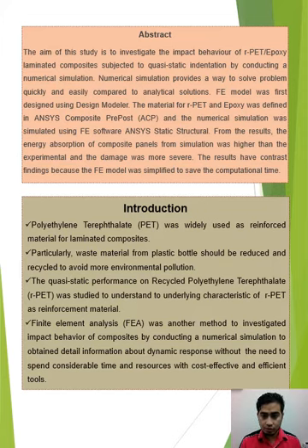From the results obtained in the simulation, the energy absorption of the composite panels from the simulation was higher than the experimental, and the damage was more severe. The results have contrasting findings because the FE model was simplified to save computational time.